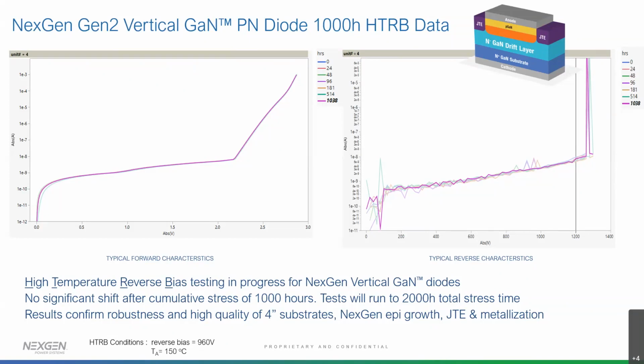So what you see here are data after 1,000-hour HTRB tests at 960 volt reverse bias and 150 degrees centigrade. And you see different readouts over time. There's no major deviation from the starting readout to the 1,000-hour readout, and we're continuing this test ongoing in our fab. Different lots are being tested all the time. That confirms basically that the major steps of the device build-up are solid, and there are no hidden reliability issues in the device construction.